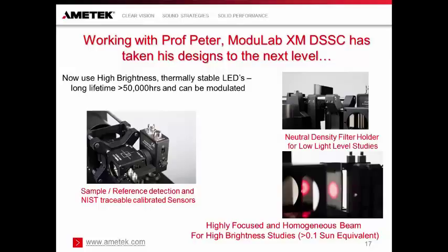impedance spectroscopy and IMPS transfer function techniques, it is critical that the input, i.e. the light, is stable during the course of the experiment. If the LED has not been optimized to be thermally stable, then the output will change, thus invalidating measurements. In addition, LEDs have a long lifetime, greater than 50,000 hours, and can easily be modulated. So they are the perfect tool, and indeed Professor Peter now uses the same LEDs that we offer with our system. In addition, we have condensed sample reference detection technique and make use of NIST traceable calibrated sensors.